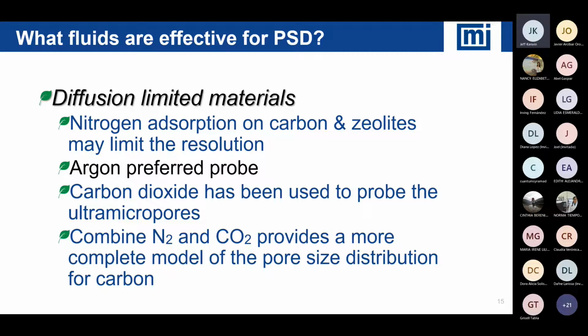Material-wise, and this is very significant with respect to metal organic frameworks, zeolites, and carbons now, from the new material perspective, we're seeing more and more materials that may be diffusion limited with respect to characterization techniques. And some of these diffusion limitations are coming into play for things like nitrogen adsorption, particularly on carbons and zeolites. The IUPAC recommendation is to use argon, but you'll see some limitations we have with argon.